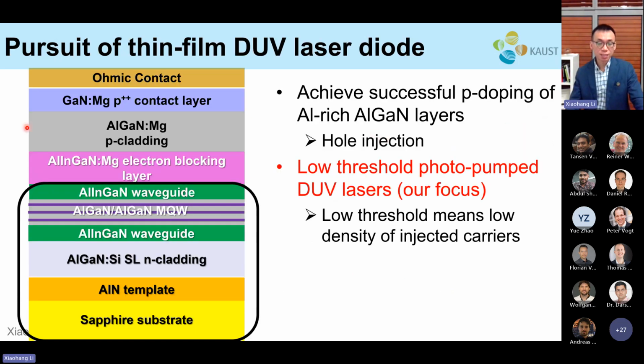So to realize the UVC laser diode, you have to do 2 things. One is to achieve very nice P layers, because one of the major issues for the high aluminum diode is the hole injection, right? So you need to have a decent conductive film for the hole injection. But also you need to have a very good cladding layer as well as a quantum well together with waveguide as well, because then by combining with a good hole injection, you can realize the good UVC laser diode.